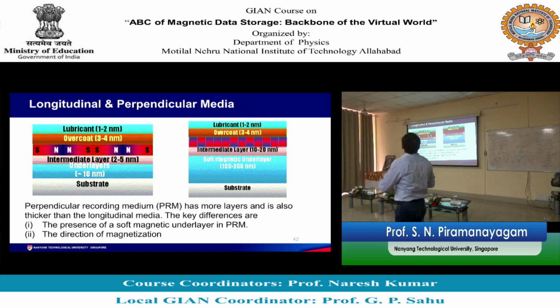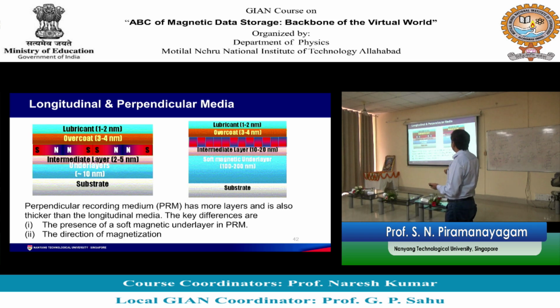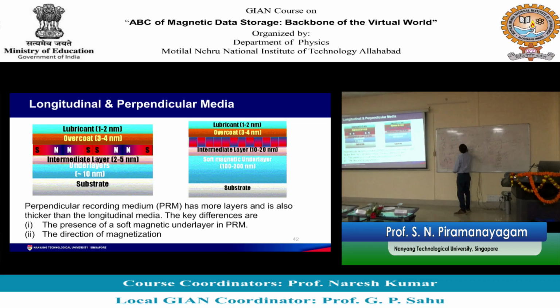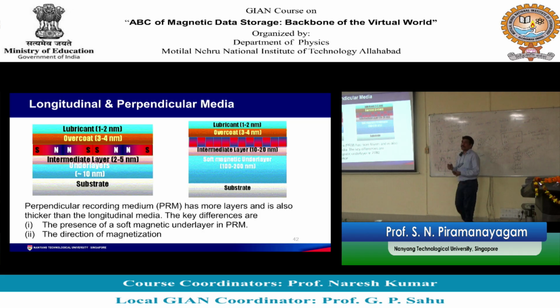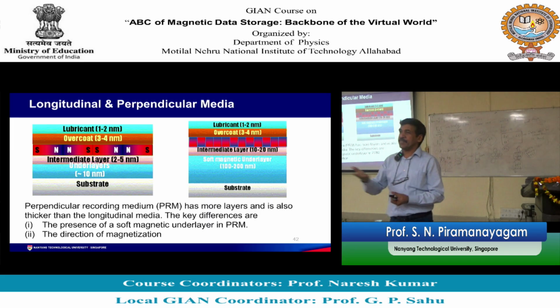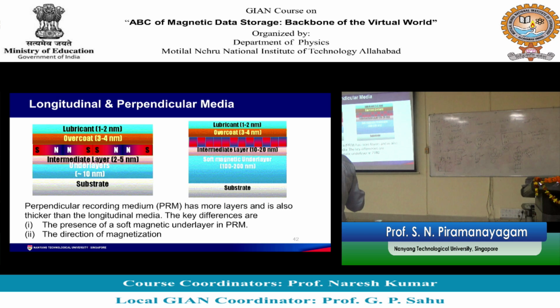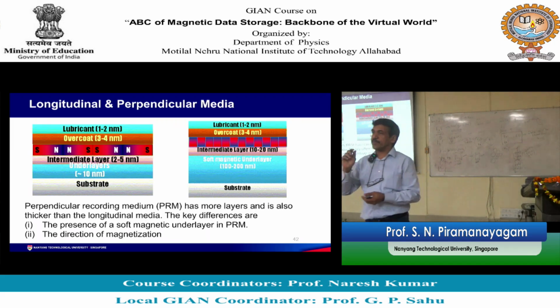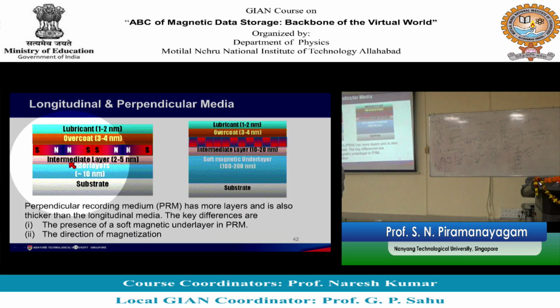Underlayer is some layer under the magnetic material. That's why we have this name underlayer. But this layer is used for controlling the C-axis structure. Okay, suppose you take a substrate and you grow a cobalt film. You go to the lab, put a silicon substrate in the sputtering machine, try to grow a cobalt film. Then the cobalt film will usually have the C axis in all random directions. In some region the C axis will be like this, some region the C axis will go this way. So you will have very random growth. You cannot make all the C axes of cobalt grains parallel to the disk surface. On the other hand, if you grow some underlayer, I told you chromium.